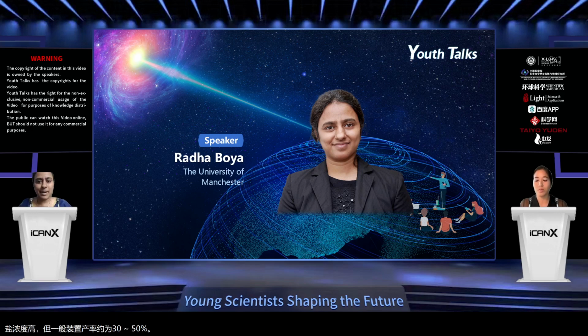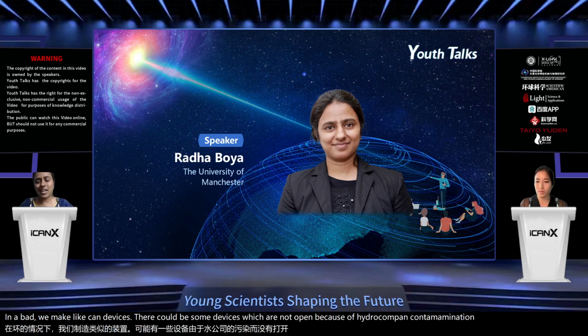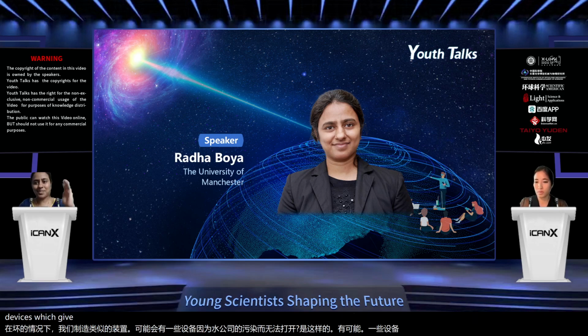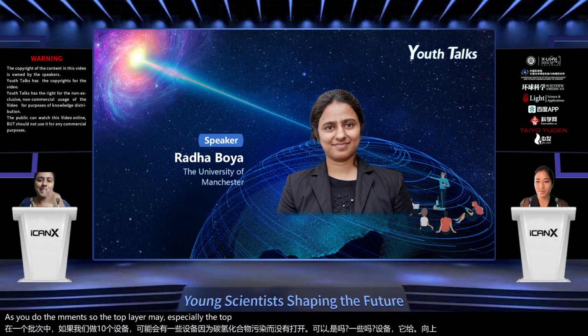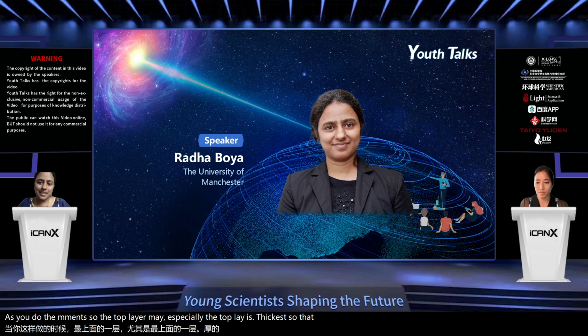In a batch, if we make like 10 devices, there could be some devices which are not open because of hydrocarbon contamination, or there could be some devices which give up as you do the measurements. The top layer, especially, is the thickest, so that can come off if you subject it to high voltages. So that is possible. So there is a compromise in how much yield of devices you can get.